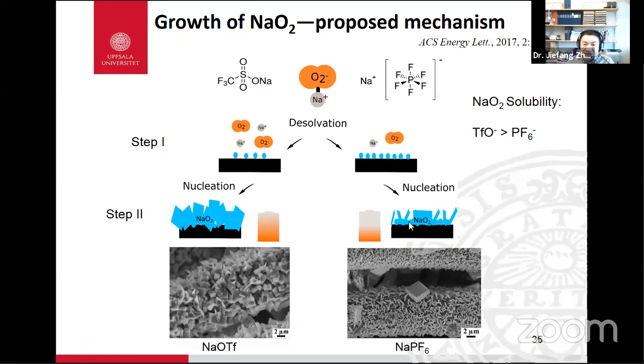So you get this. But since sodium superoxide has very low solubility in NaPF6, it prefers to grow on the existing sodium superoxide. That's why you see the big blocks.